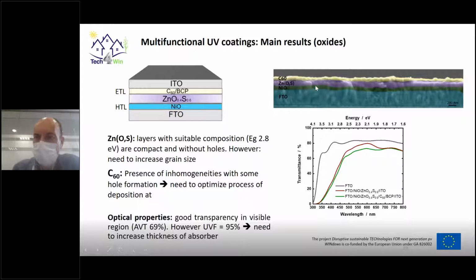However, we have already seen that we need to increase the grain size, because the grain size is really very small. And the main limitation in this case may be related to the C60 layer, where we can see the presence of inhomogeneities in some places, for example in this region on the right-hand side, where there are even some holes. Of course, this leads to degradation of the photovoltaic performance of the devices. So we already know that we need to optimize the deposition process of the C60 layer.